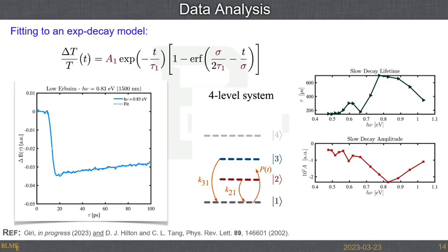So we're actually somewhat astonished that the number, instead of being 0.8 eV, was actually 0.83 eV. That's a remarkable agreement. It is a testament to how much he's been working with and understanding this material. It shows that he's created a robust absorption in this material in exactly the wavelength you would need to create a modulator out of all of this. And then you've got a lifetime here that's less than a nanosecond.